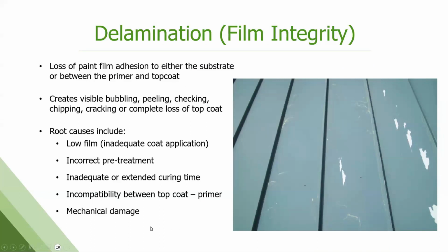Paint delamination. This is a really tough one. This is loss of paint, either the top coat from the primer or the whole system down to the substrate. It can present as bubbling, peeling, cracking, different ways. There's actually, I think I'm up to probably 75 different root causes for this, but I've listed the most common ones here. Low film, that's on the coater. Incorrect pre-treatment. If your pre-treatment and cleaning of that substrate wasn't good, you may not have gotten good paint adhesion to the surface. If your curing of the paint wasn't good, this can happen.